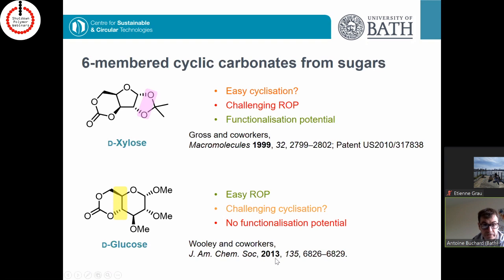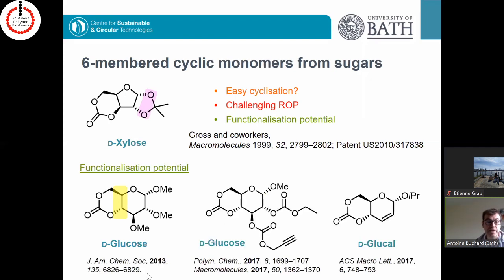Wooley and co-workers in 2013 also published this really nice molecule here from D-glucose, which solved in part the problem of the ring opening by looking at this type of really strained trans 6-member cyclic carbonates. But in that case, unfortunately, because those other OH groups were basically stuck in the O-methoxy form, there was no functionalization potential possible. However, it must be said that further down the line, these things have been addressed, and this is the group of Karen Wooley again, where they've made a variety of those glucose derivatives, where clearly they've shown that there's a lot more chemistry that you can do once you replace those groups here.